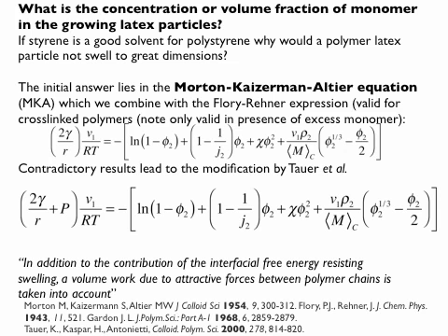And then the last bit in this equation is a correction term. This correction term is the Flory-Rehner theory and basically deals with crosslink density. V1 in this particular case is the molar volume of the solvent, in this case the same as the molar volume of the monomer.